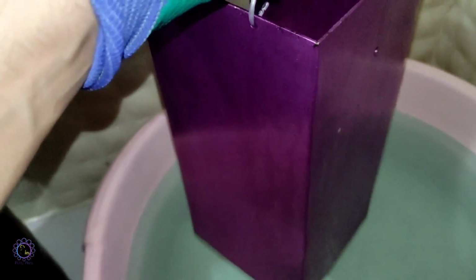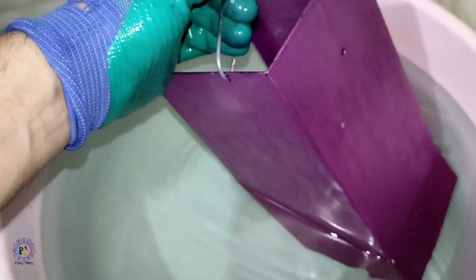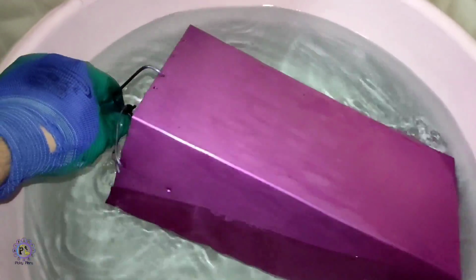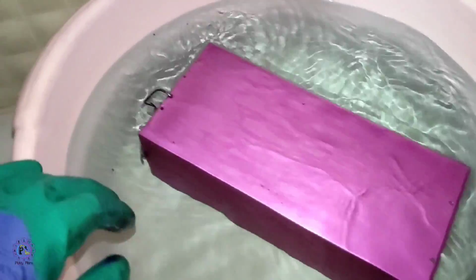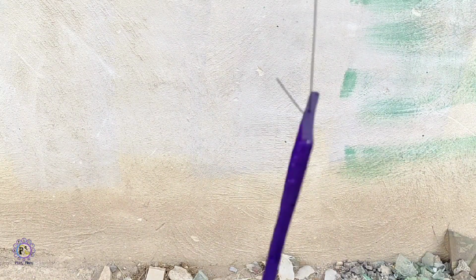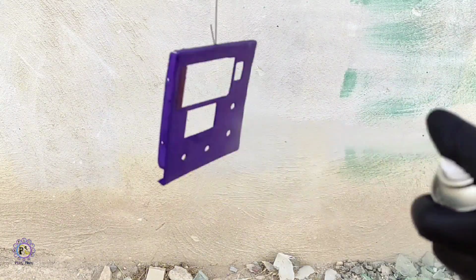Next, the colored part was added to the nickel salt bath to become sealed completely. Normally I shouldn't paint over anodized aluminum, but I decided to cover part of it with polyester based coatings to insulate the casing and also protect the color.